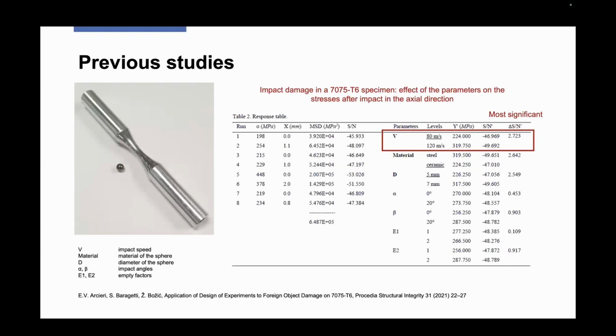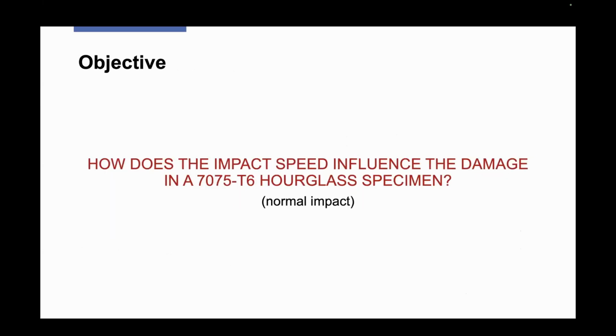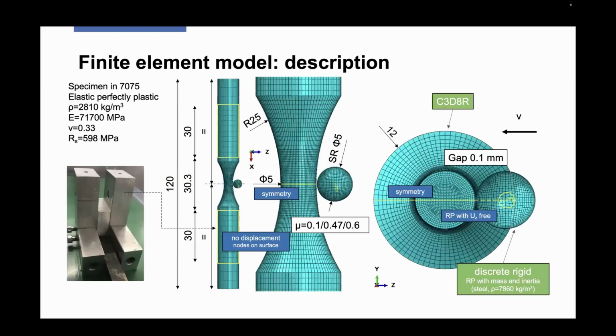According to this study, we found that the impact velocity is the most significant parameter on the stress state in our specimen. And so for this reason, the objective of the presentation of today is to discuss how the impact speed influences the damage in a 7075-T6 hourglass specimen to find the trends. And due to the fact that we have found that the impact angles are not so significant as the impact speed, we are considering only normal impact.